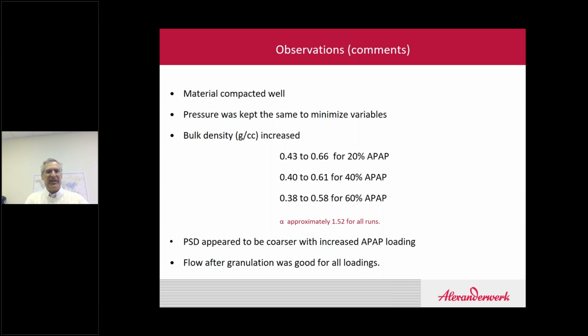Let's take a look at some of the observations of the material that we saw in the end. The material did compact very well. It was a good blend. It ran smoothly. There was no sticking to the rolls. The pressure was kept the same to minimize the variables from one drug loading to another. And you can see the bulk density did increase. If we look at the 20% APAP loading, our bulk density increased from about 0.43 to 0.66. Keeping the same parameters as I indicated, the 40% APAP drug loading took a bulk density from 0.4 to about 0.61 grams per cc. And for the highest drug loading, we went from 0.38 to 0.58.